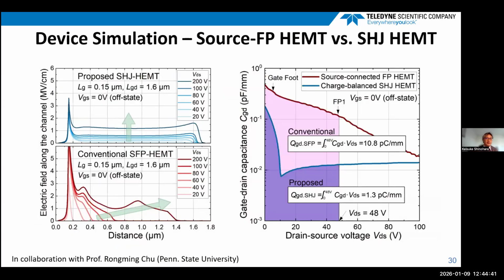So this is a device simulation result comparing the source field plate device and super heterojunction, which was performed by Professor Rongming Chu at Penn State University. As illustrated in the previous slide, the super heterojunction shows the uniform electric field, while the source field plate device shows the laterally expanding field distribution with increasing drain voltage. And on the right, it shows the gate-to-drain capacitance as a function of drain voltage. And as you can see, the gate-to-drain capacitance for the charge balance super heterojunction, shown in the blue lines, is much smaller than that of the source field plate devices. And it drastically reduces the gate charge in between the gate-to-drain regions.